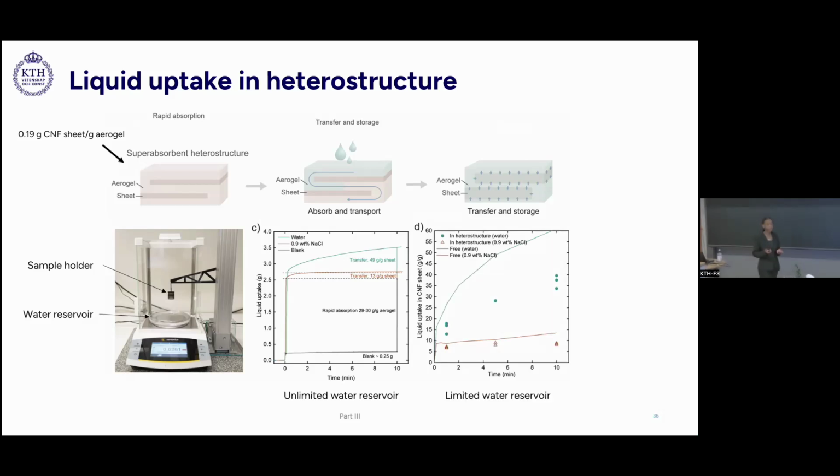We then performed a similar measurement. However, this was done in a limited water reservoir, which is a volume of water below the saturation capacity of the aerogels. And we then measured the liquid uptake in only the CNF sheets. And here we found that the liquid uptake in the CNF sheets was quite a bit lower. However, it still demonstrated a rather efficient transfer of liquid from the aerogels to the CNF sheets. So this was another demonstration of how we can then utilize the liquid uptake in fibrillar structures to design modern hygiene products.